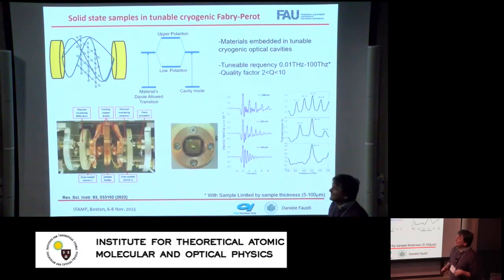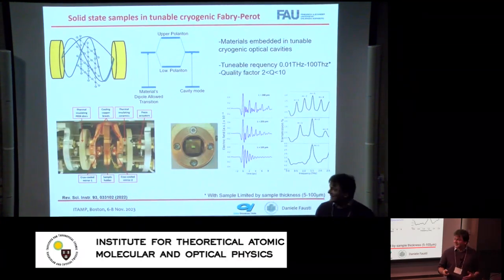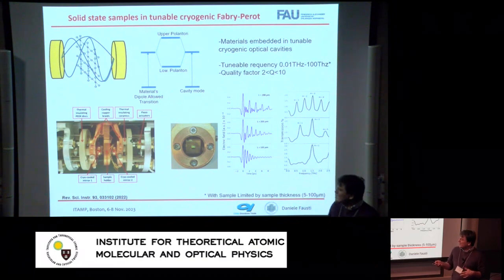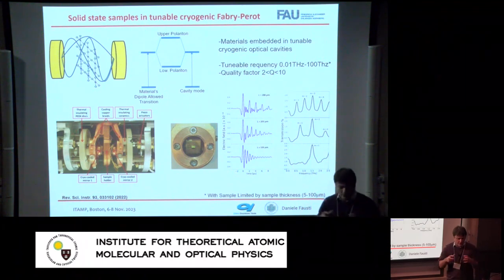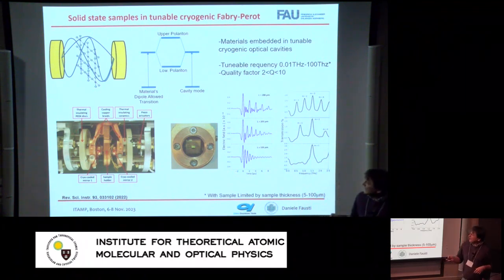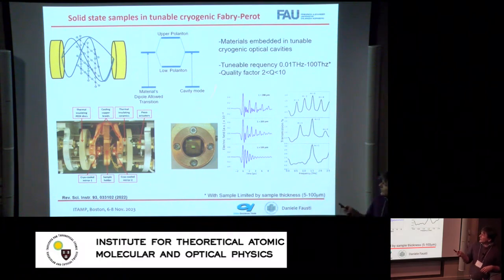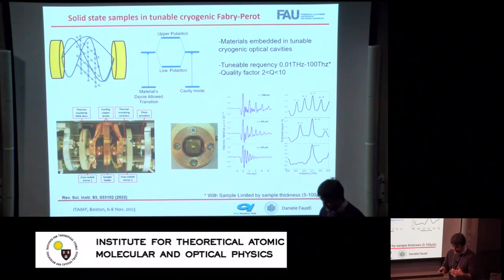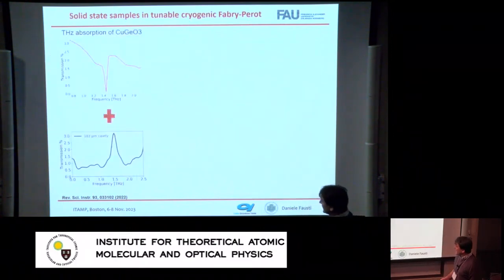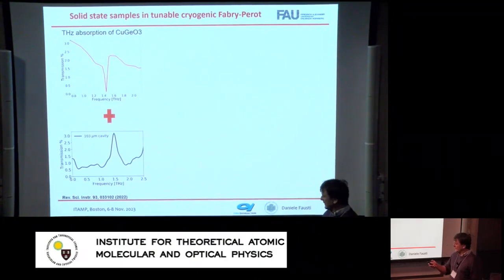So it's a very vivid place to be at the moment. So we have developed our own settings to try to test this. Essentially we have samples in Fabry-Perot cavities. They are all cryogenic, so we can control cold mirrors. And the idea is that once you tune your cavity resonance to the material transition, you could think of forcing this exchange and increasing the interaction, describing it in terms of naive Rabi physics.